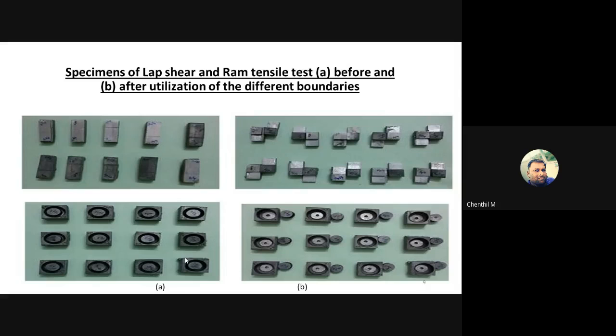In the ram tensile strength measurement, a standard specimen was used to determine the bond strength, whereas a bonded plate with a hole, with one side diffusion bonding, and the larger side was weaker than the other side. This made a testing fixture, and the ram pressure force loads the bond in the tension area. The sample test before the application of tensile force is shown with respect to the aluminum and magnesium alloy.